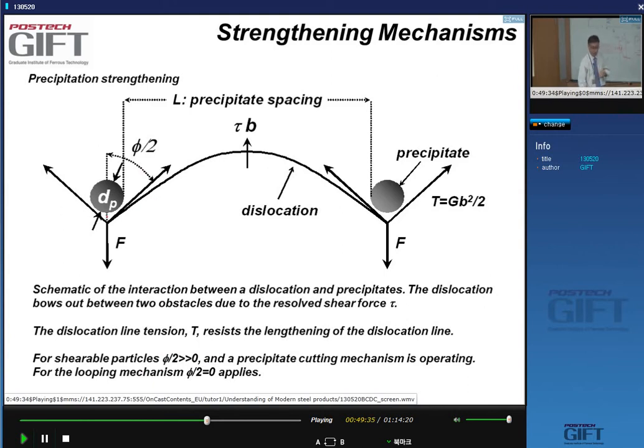So the obstacle, the particle, lets go of the dislocation at much lower critical angles phi over 2. Whereas in the case of the looping mechanism, the pinning is very efficient, and when the dislocation passes these obstacles, these hard particles, phi over 2 is 0, effectively.